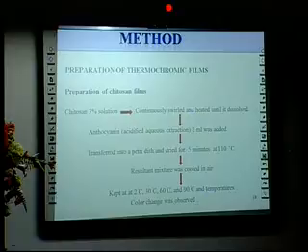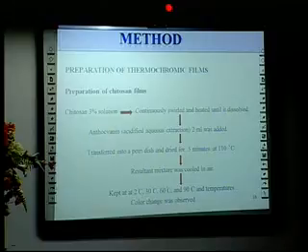Using that kinetic study data as an application, here a thermochromic film was developed. To develop a thermochromic film, we need a matrix. Here we use chitosan, agar and agarose as matrices, but only chitosan gave a positive result. The following procedure was used to form a film, and the film was kept at different temperatures and the color change was observed.